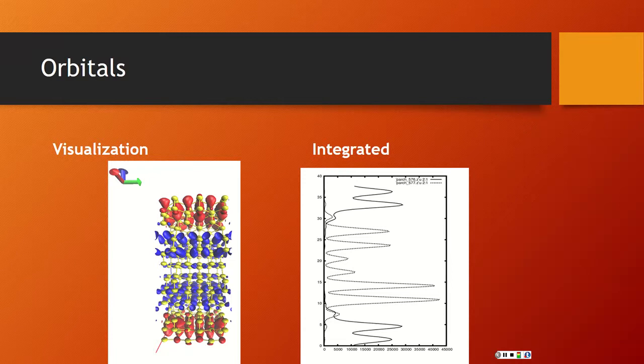At first, I was not entirely sure how to explain that, but what I tried doing, unfortunately, after I put the presentation together, was I looked at the LUMO+1 and the HOMO-1 and plotted those orbitals. And what you see is actually the reverse of this. The HOMO, like before, is localized around the p-dopant, and the LUMO is localized around the n-dopant.